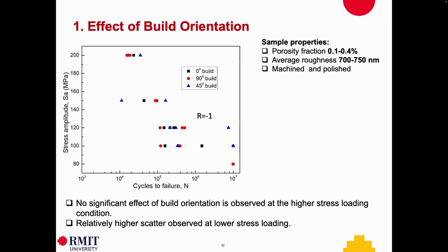Now, at a high stress amplitude, what we found is there is less scatter and little effect of build orientation, which was kind of contradictory when we found it. At a low level of stress amplitude, we again don't find a good correlation, but we find a larger scatter of data for these three build orientations we tested, 0, 45, and 90. We used a porosity fraction that is not too big, very small, 0.1 to 0.4. Average roughness was less than 700 nanometers, and we machined and polished. So we wanted to suppress the effect of porosity and roughness. We want to highlight what is going on with the build direction.